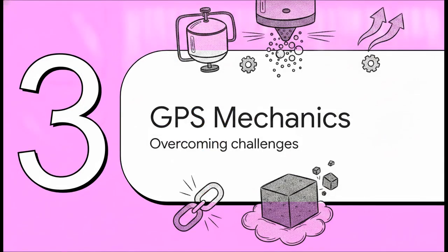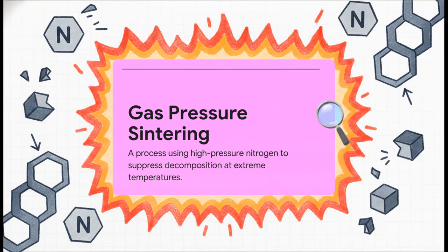Which brings us to Section 3, gas pressure sintering mechanics. So, how do we actually clear those high-temperature hurdles for commercial viability? Well, most industrial silicon nitride relies on a process called gas pressure sintering, or GPS. Here's the catch. At the extreme temperatures required to densify, silicon nitride actually wants to decompose. By applying a high-pressure nitrogen atmosphere, GPS essentially forces the material to stay intact. It completely suppresses that decomposition while it reaches maximum density.